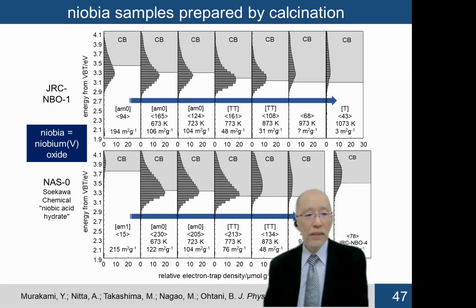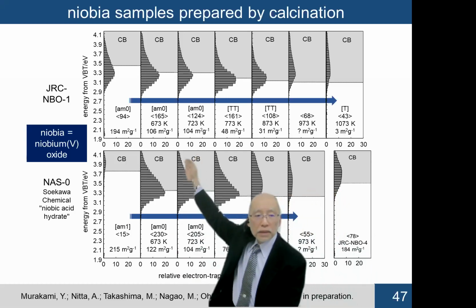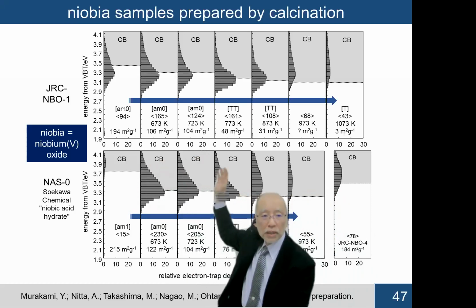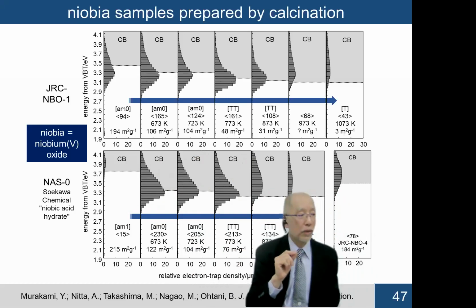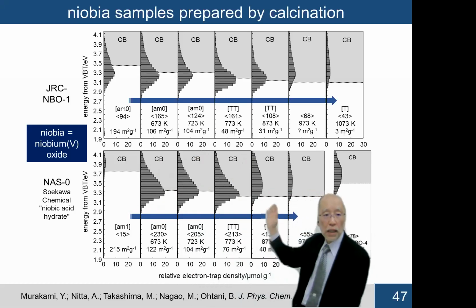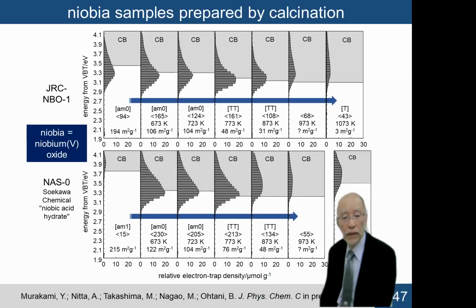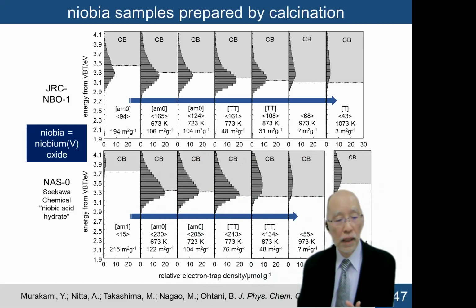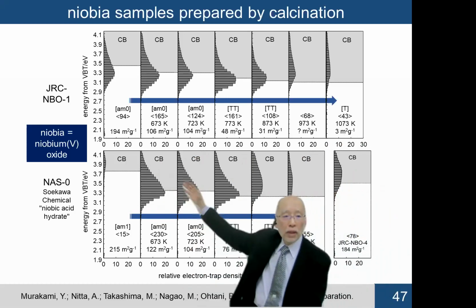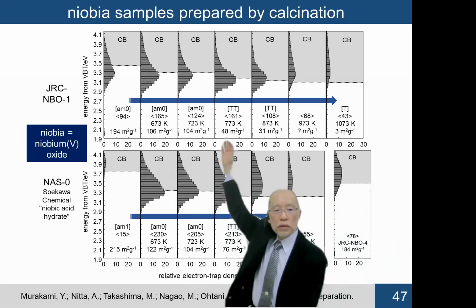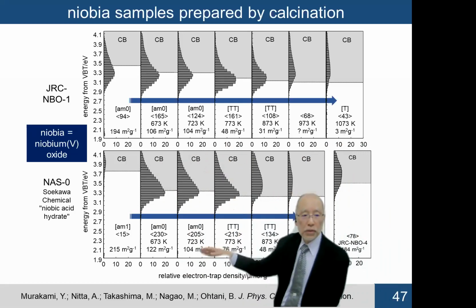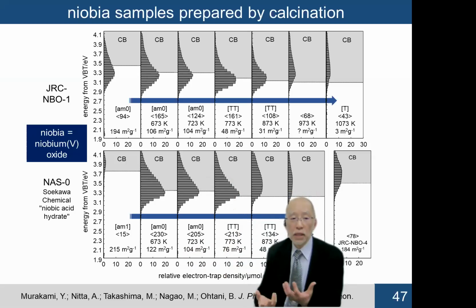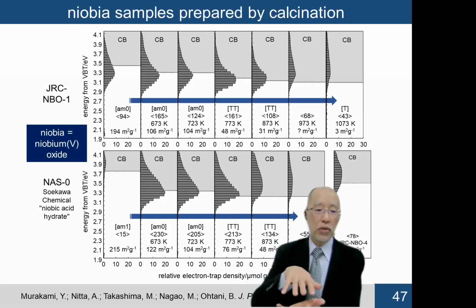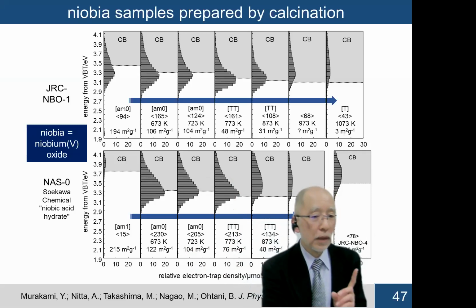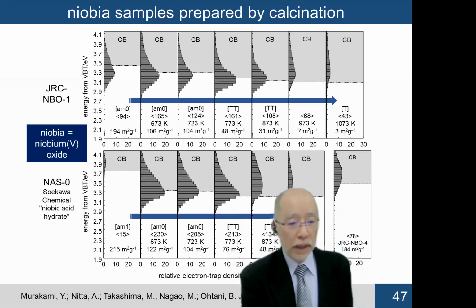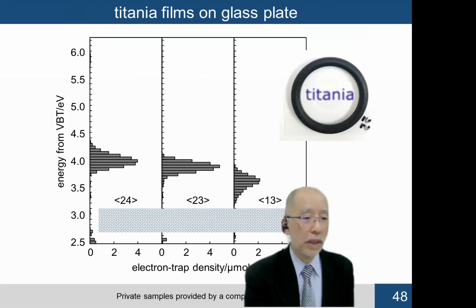All six samples are amorphous, and this is TT, the name of a crystalline phase of niobium. The TT and T crystalline phases are detected in XRD. But you can see that for TT materials, the peak position of the ERDT is a bit lower compared with the amorphous one. So that reflects the surface structure depending on the bulk structure, amorphous or crystalline. So even for amorphous or amorphous-containing material, it is possible to analyze by using this technique.